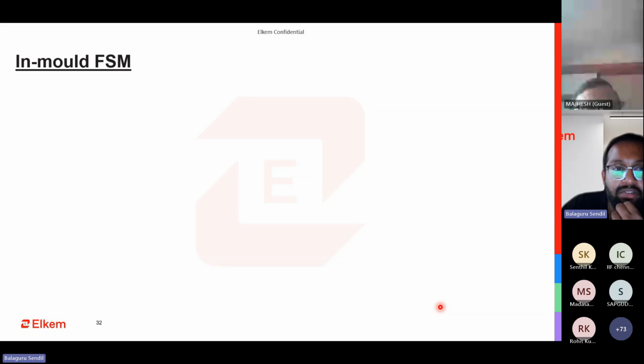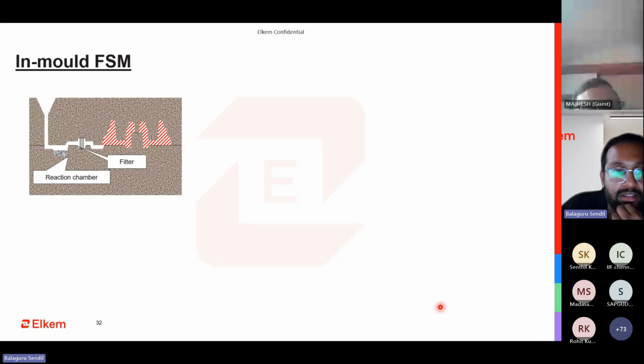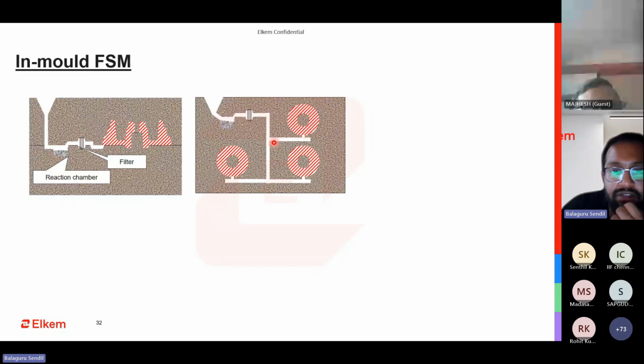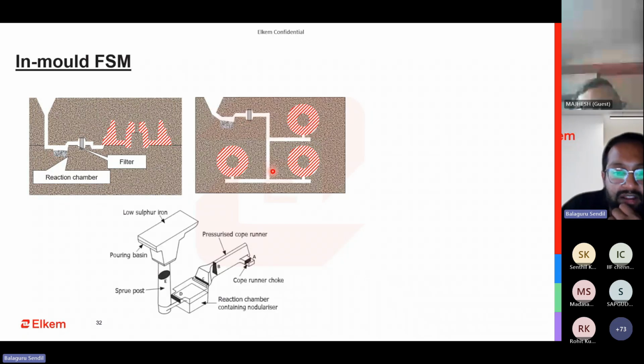This in-mold FSM is the next part. This is something not so common in India. Only few people are doing. You have a reaction chamber inbuilt into your gating system where you keep the ferrosilicon magnesium. You put a filter and the casting is there. So there are different orientations possible. And then this reaction chamber has to be designed very specifically so that it will be able to accumulate that amount of material. So it gives you a recovery of 85%.